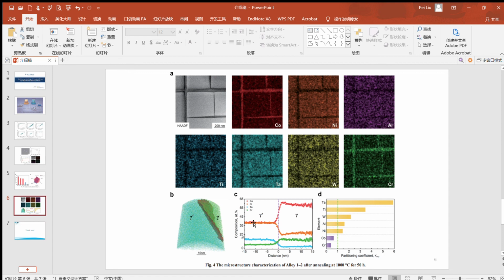The best performer, this Alloy 1-2, possesses the highest gamma-prime solvus temperature of 1266.5 degrees without the precipitation of any deleterious phase, a gamma-prime fraction of 74.5% after aging for 50 hours at 1000 degrees, a density of 8.68 grams per cubic centimeter, and good high temperature oxidation resistance at 1000 degrees due to the formation of a protective alumina layer. Our approach paves a new way to rapidly design multi-component materials with desired multiple properties.